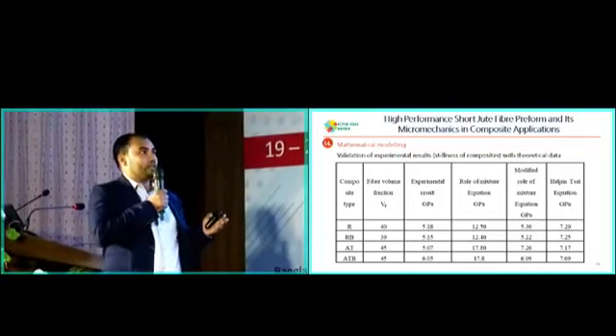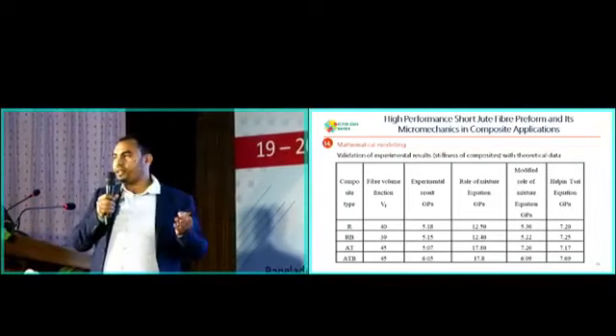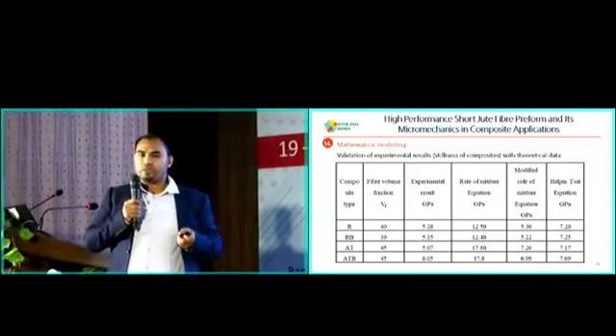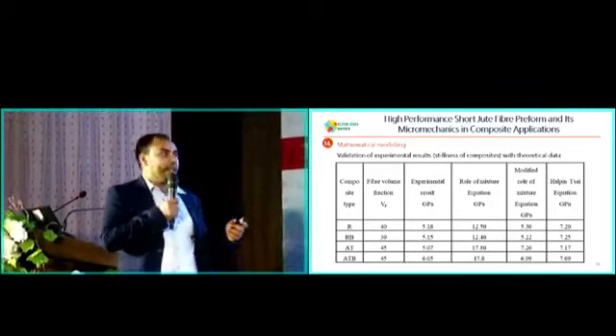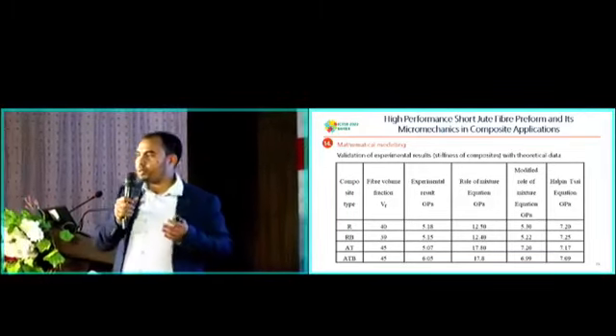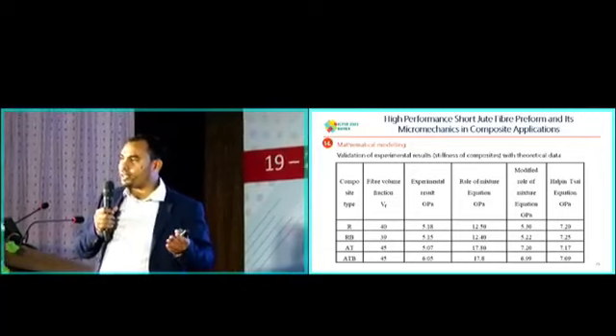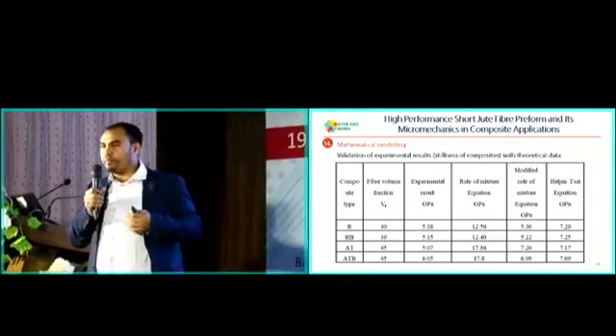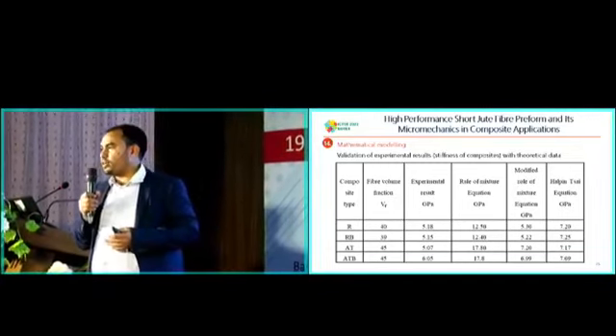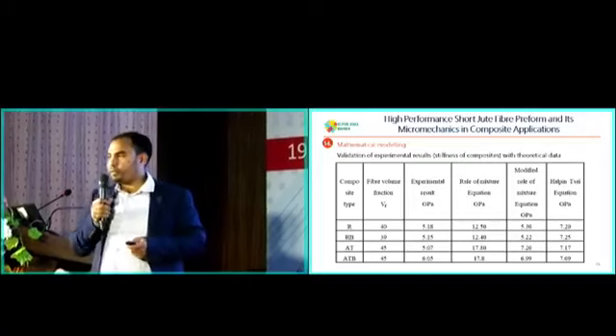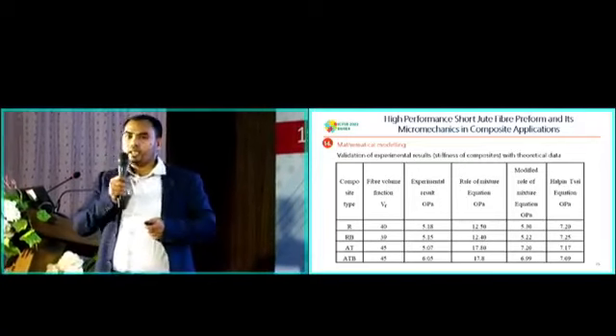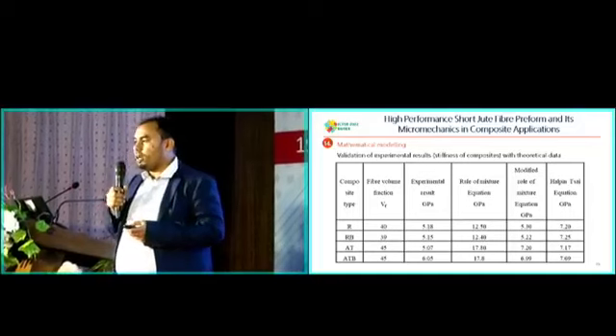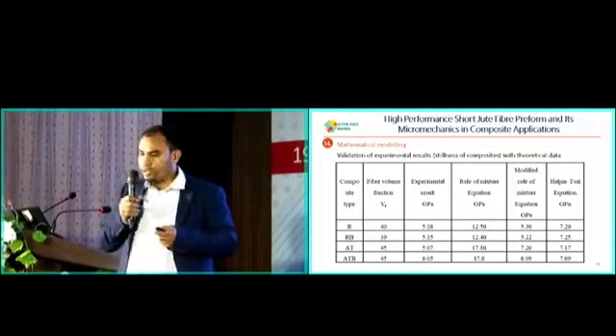Similarly, we use the Halpin-Tsai equation. It gives you nearly comparable data. So that means the claim that we claim in our work, that we have produced a high performance, densely packed short jute fiber preform, which can be replaced for the glass application, is basically validated by the mathematical model data as well.